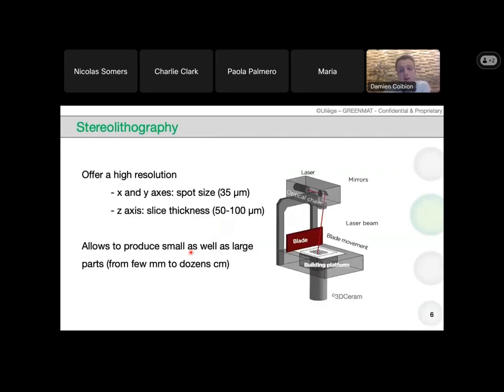So why did we choose stereolithography? It's mainly for two reasons. The first one is its high resolution, which is mainly defined by the spot size. Here we have a 35 micron spot size of the laser, and by the slice thickness, we are working with 50 to 100 micrometer layers. And also it allows us to produce small as well as large parts, from a few millimeters to a dozen centimeters, that can fit the defect.